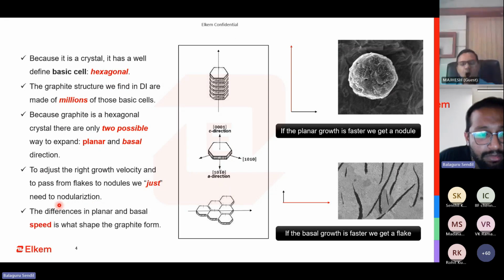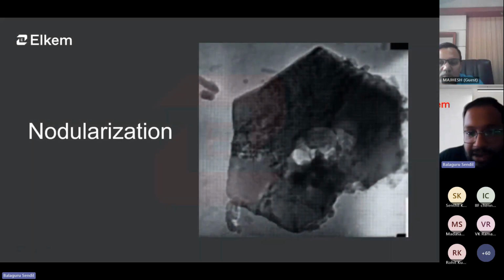What does nodularization mean? It is a process of introducing magnesium, which makes sure that the speed of this particular plane, that is the planar, is growing faster than the basal. So the speed difference is very critical to form a very good graphite shape. So this is the basics in which the nodule grows. And whenever we see there is a mismatch in these growth rates, you get a degenerated nodule, which doesn't have any useful mechanical properties.